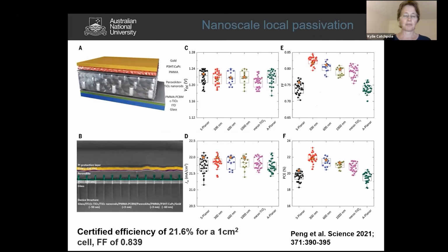So recently, we've developed this further, and what we've looked at is a nanorod structure. So what we've got here, if you look at the top left, we've got some titanium dioxide nanorods, right? And a combination PMMA PCBM passivation layer on the bottom, and this defined nanorod structure. And you can see it here quite clearly in the cross-sectional scanning electron micrograph. And what we see is that especially this structure leads to a significant improvement in fill factor.